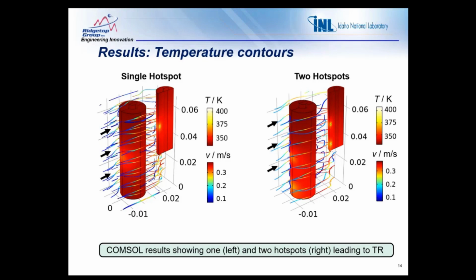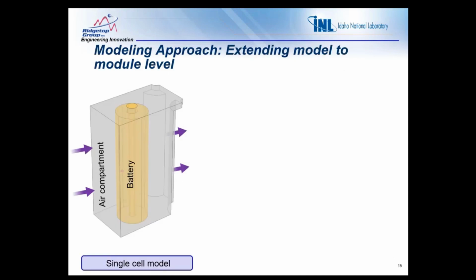While airflow can moderate the overall temperature, it cannot entirely counteract the localized heating caused by hotspots. This is evident from the persistence of maximum temperature at hotspot locations. By comparing the two cases, we see that multiple hotspots not only elevate the overall temperature but also intensify the thermal instability within the battery. This highlights the importance of precise hotspot management and robust cooling strategies to delay or prevent thermal runaway.